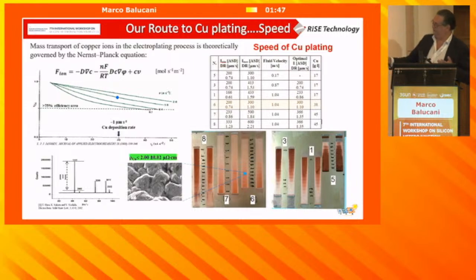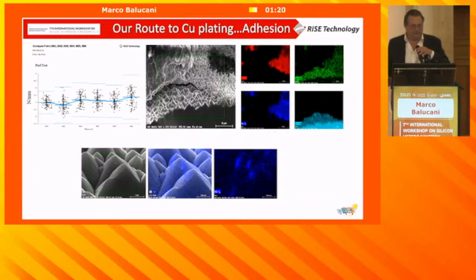And we have a very nice quality of copper, the resistivity is very good, and because we have less 200 orientation, this means that even at high current density, there will not be a migration of ions and so on. We measured the adhesion with this test, and what we wanted to test is where we have the breaking. Mainly the breaking, if you see it, here it's shallow, but from this EDX analysis, you can see that we don't break the silicon. And we have an adhesion that is around 3 Newton per millimeter.